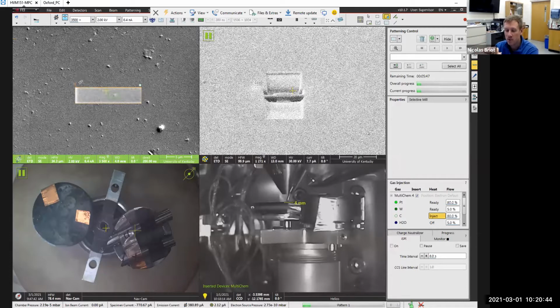But before I start using the focused ion beam, I actually want to protect the surface a little bit, because as soon as I use the focused ion beam to get an image, just to position where I want to do the cuts, I'm going to destroy the sample. I'm going to start modifying and milling the surface of the sample. So if you're trying to study something that's very close to the surface, of course, you don't want to mill it before you even have the chance to do a proper cross section.